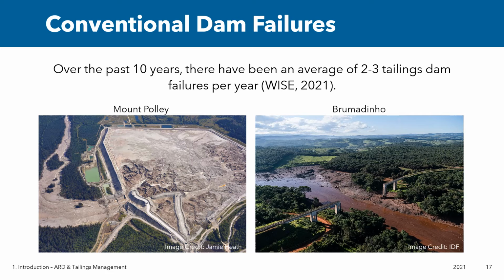Using the data compiled by the World Information Service on Energy for major tailings dam failures, there have been on average 2 to 3 tailings dam failures per year since 2011. In the wake of the Mount Polley failure in 2014 and the Brumadinho failure in 2019, the industry has been under increasing pressure to find alternative tailings storage methods to reduce risk.